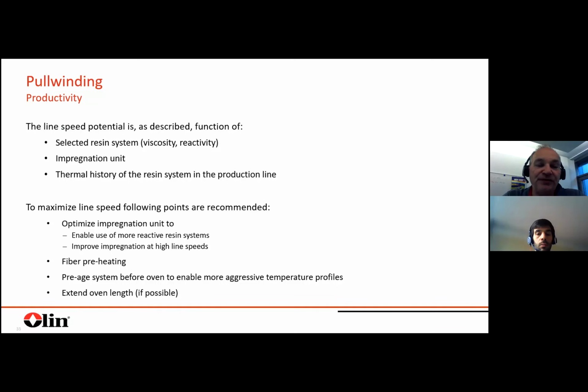Pre-age the system before the oven. As mentioned, it's helpful to control the resin flow at the oven entry. Which also means, if it is not required to put high effort into avoiding this resin dropping, you can be more aggressive with the temperature profile right from the beginning in the oven. So that means you can run faster. And for sure, the simplest one would be just to extend your oven length.